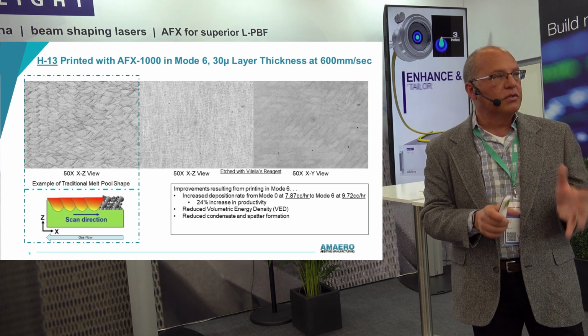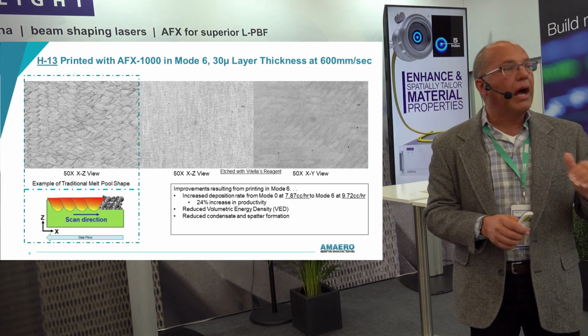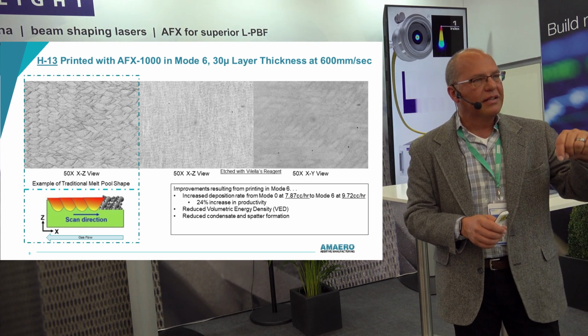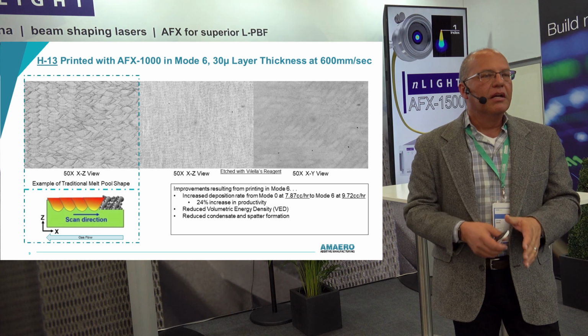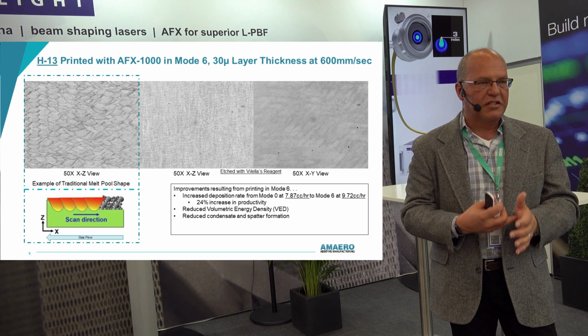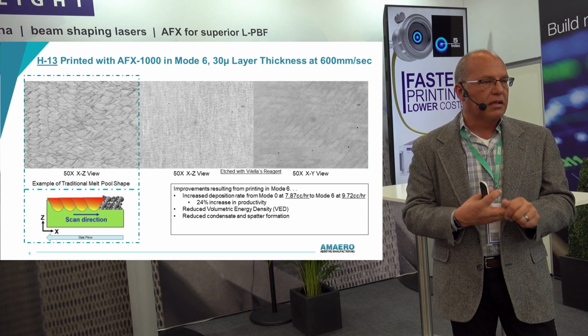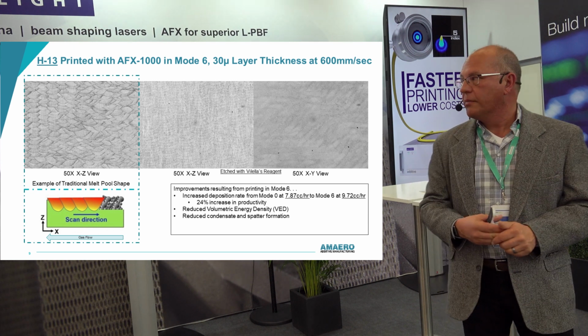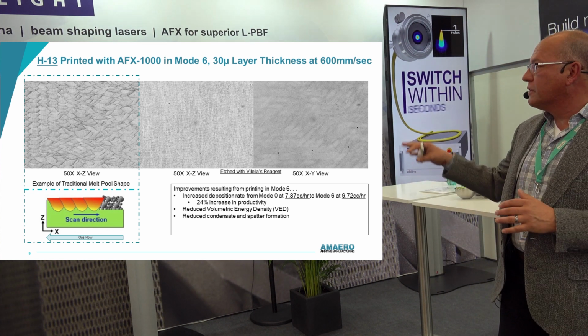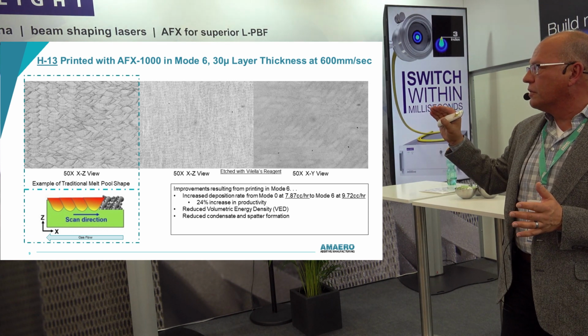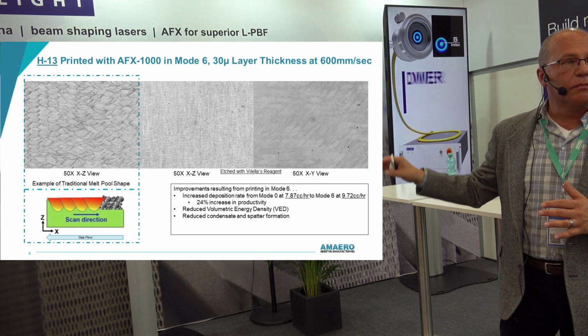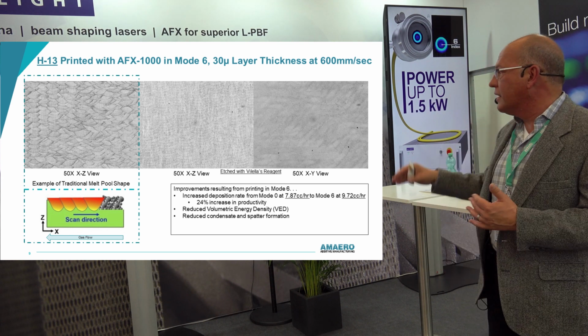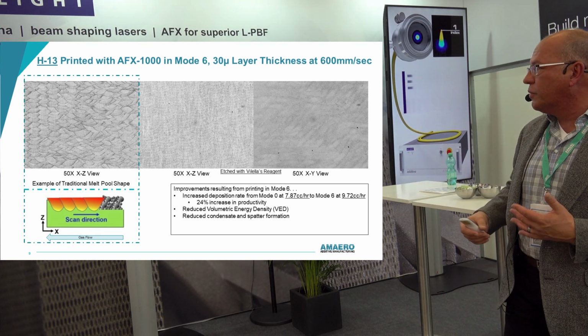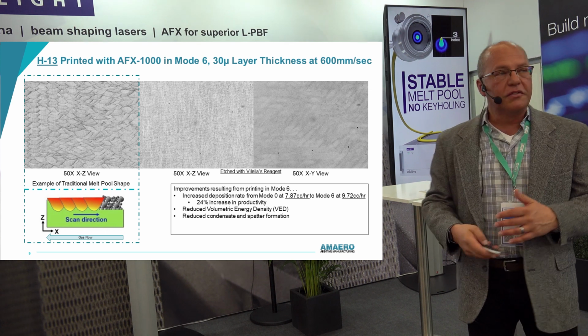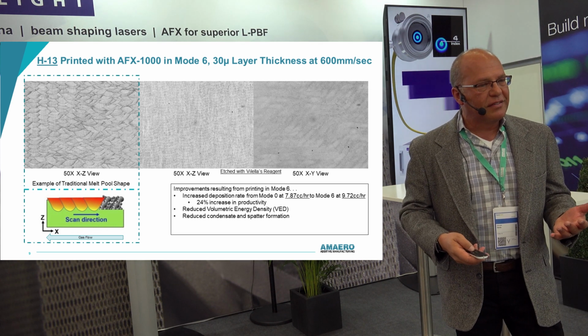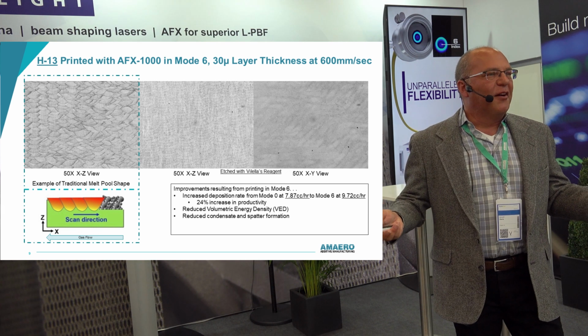It allowed us to reduce the total laser power because we weren't wasting all this Gaussian power in the middle. So we reduced the laser power, widened our hatch spacing, reduced the condensate generation, lowered the volumetric energy density, and we took, I mean, this was impressive. So H-13 is very unproductive, 7.8 cc's per hour. We got it up under these conditions to 9.7. That's a 24% increase. But I was just so amazed at how well this worked that I had to see how far I could take it.